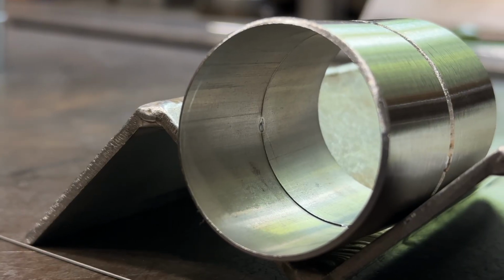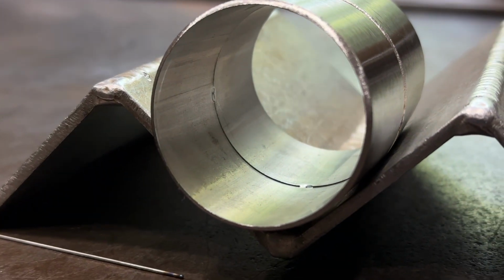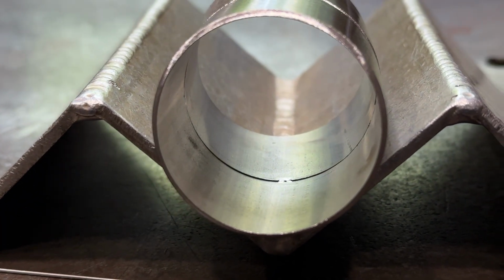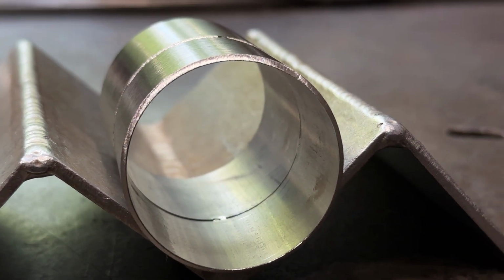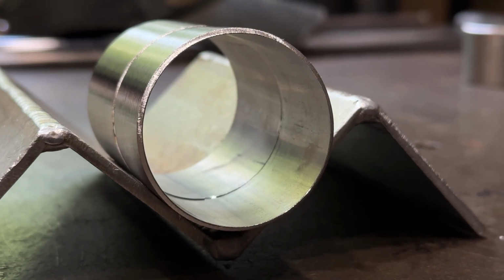The purged tacks, again, if we look on the inside here, you can see a nice little silver tack there, same there, same there, and then the fourth one, same there. And if you purge your tacks, then you provide a nice purged little spot weld essentially to run over easily with the actual weld that you're doing on the piece without pulling any crap into it, making nasty spots that inevitably will be in the most visible portions of the piece that you're working on, and it's just a bad deal. So my advice to you is on any reactive metal, just purge your tacks. It takes a few extra moments to set up, and it takes a little bit of getting used to, but the benefits are massive, and I really think that the effort is worth it.